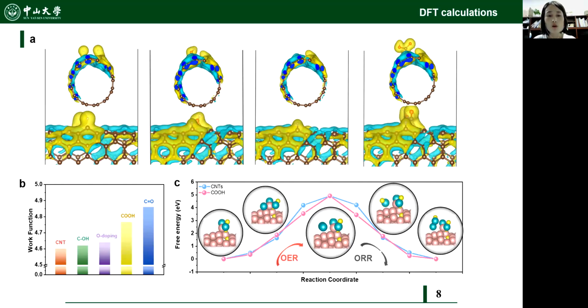In addition, all OCNT samples showed higher calculated work functions than pristine CNTs, indicating oxygen regulation could effectively modulate the electron density of CNTs, which is also confirmed by experimental results. The reaction free energies of the reaction pathway are calculated, demonstrating that oxygen functional groups can boost catalytic activities of CNTs for both ORR and OER.